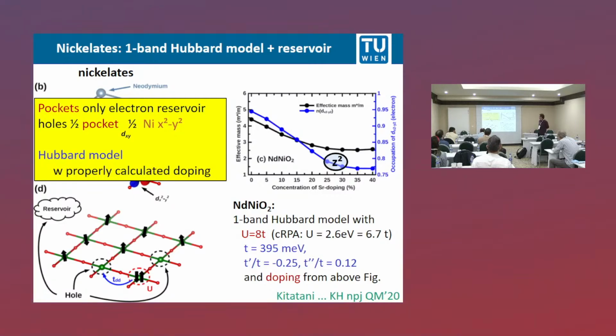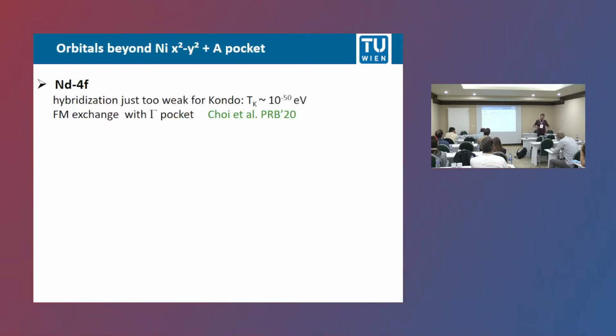But let me also point out that at larger doping, this z squared orbital becomes then occupied or deoccupied, so occupied with holes, depopulated with electrons, and therefore you have this change of slope here for larger doping. There are quite a number of other theories for the nickelate. So at the beginning, people were very much excited when you only had neodymium nickelate, that wow, now you have an f electron superconductor, and people thought it is relevant.